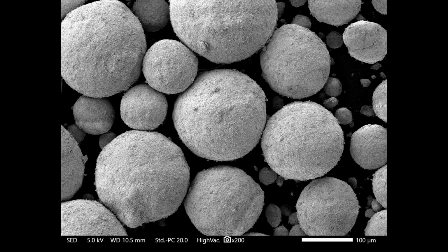And then you said you agglomerated, and I understood you were going to compact it, to press it uniaxial. Why is it necessary to agglomerate it prior to compaction? Yeah, well, I think there are several reasons for that, but at least one point is that hard metal powder is really hard. So basically, if you try to compress it just by itself, it doesn't do anything. You can't have a green state product. So it first of all requires some kind of a binder, usually some kind of a polymer or paraffin wax binder, and